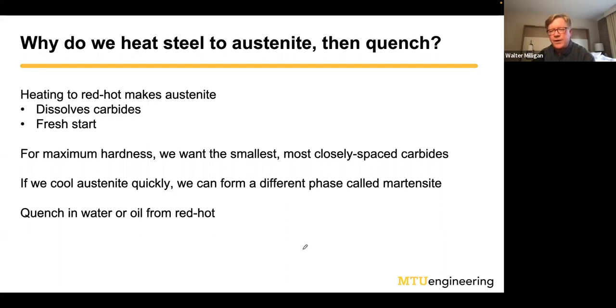The reason that works is we form a new phase called martensite that doesn't show up on the phase diagram because it's not an equilibrium phase. So we're going to quench the material from red hot in water or oil. When we do that, we're going to transform the austenite into a new phase called martensite.